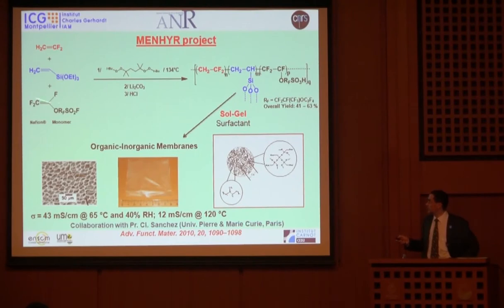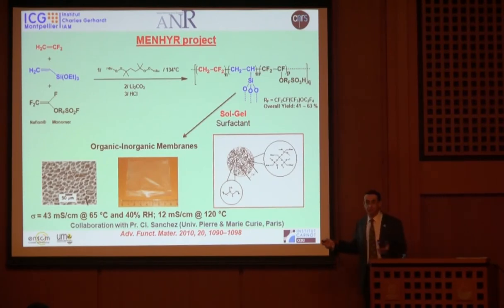and these sulfonic fluoride compounds, okay? And thanks to the trialkoxysilane, it was possible to make some sol-gel. You don't need a lot, because this vinyl compound is very poorly reactive. So let's say if we put 8% in the feed, we obtain 2% or 3% in the polymer, which is enough in order to enable the cross-linking. So it's a kind of sol-gel cross-linking that we achieve.